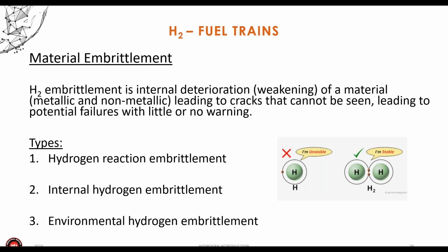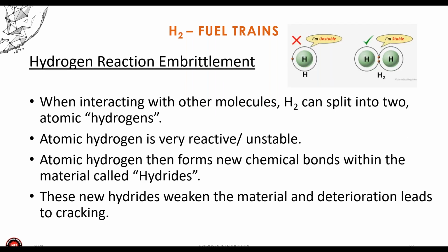The last major topic of hydrogen use is material embrittlement. Embrittlement is an interior degradation or deterioration of the material because of a hydrogen reaction to it. This leads to cracks, failures, things you can't see, in both metallic and non-metallic parts. So we've got a couple different types of hydrogen embrittlement. There's reaction versions, there's internal pressure-related embrittlement. But in general, it's when the hydrogen H2 breaks apart, which happens often, and you have a lone hydrogen atom by itself that's unstable, it's going to want to try and bond to something. So whether it bonds to iron or other materials, it'll form what's called hydride, and those hydrides tend to weaken the materials, and deterioration then starts beginning.